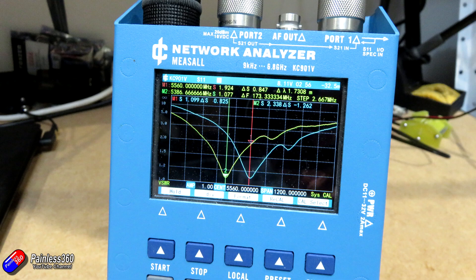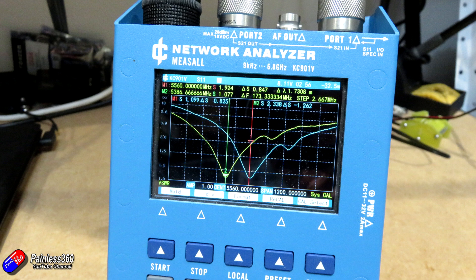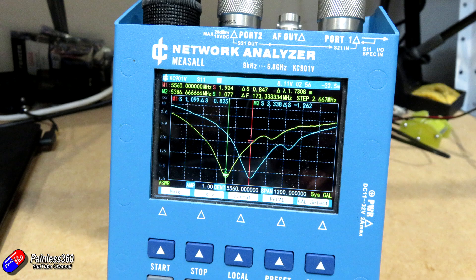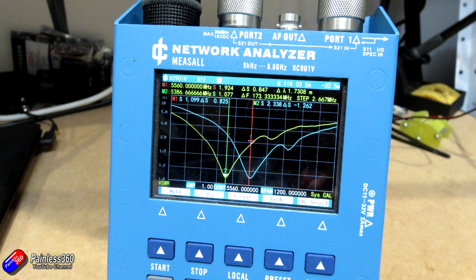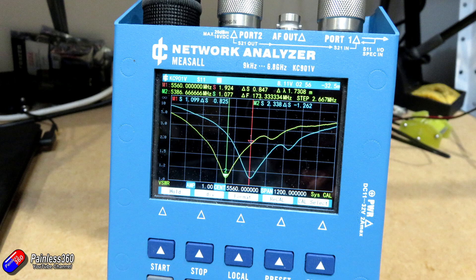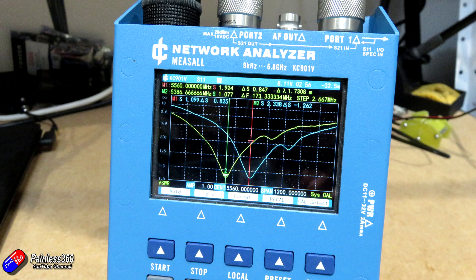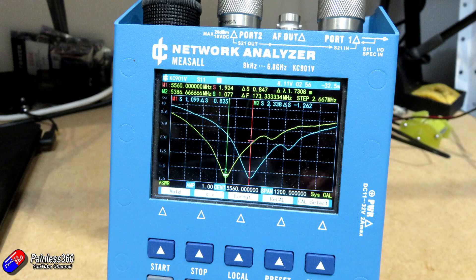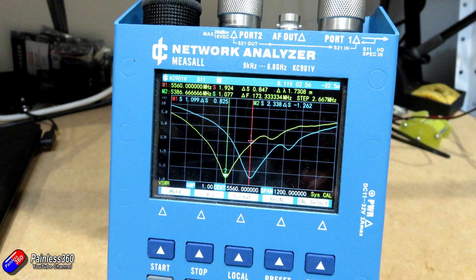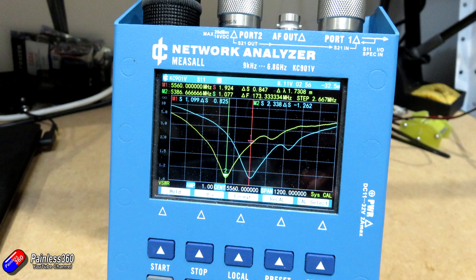So Greg, what can you see from the TPU? This is what we saw in the original video about covering antennas with 3D printed plastic. The blue waveform was the antenna without any sleeving, and the yellow trace is with the TPU sleeve. We've seen a shift of 174 megahertz down from the original tuned frequency. We've been able to repeat and confirm from the first video how it was detuning the antenna.